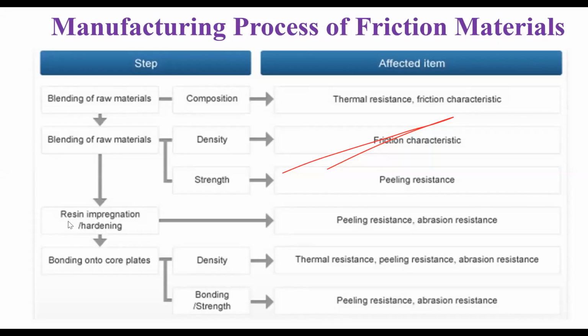After blending, what you're going to do is the impregnation of the resin along with the hardening process, which will also increase the peel strength and also the abrasion resistance strength. Finally, you're going to bond into the core plates. Then you're going to have the final density of the particle. So these are all the parts of the manufacturing process of the friction plate. And finally, you're going to ensure the bonding of the clutch plate, which will have the strength. At the same time, it will also withstand the vibration. It will not come out, as it has the peeling strength, and it also has the abrasion resistant properties as well.